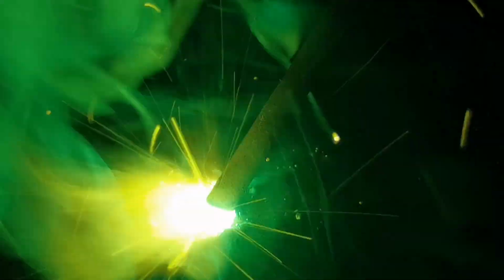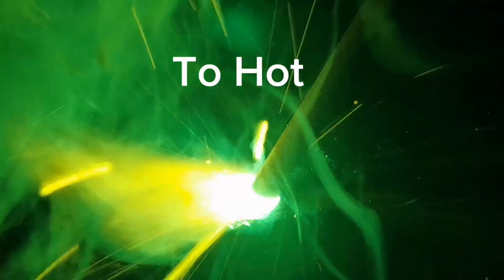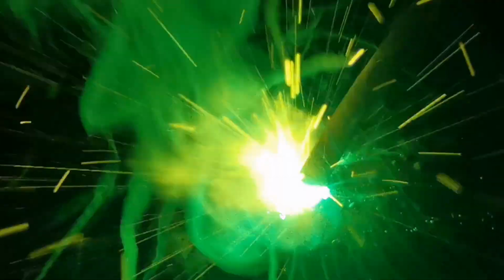Now, in this clip you can see that the welding rod is far too hot. My travel speed has to increase to keep up with the rod that's being burnt. Very hard to control the weld, and not good at all. An awful lot of spatter.